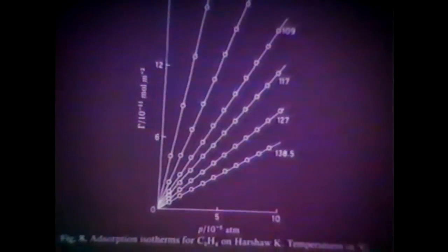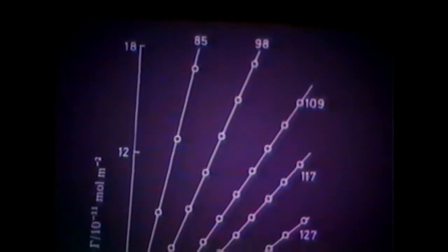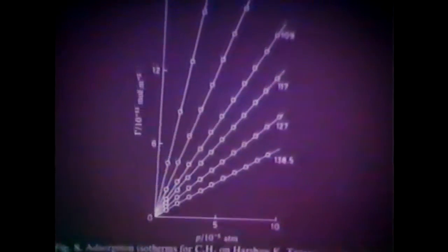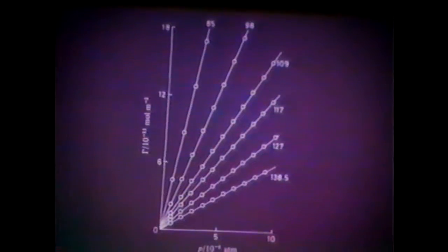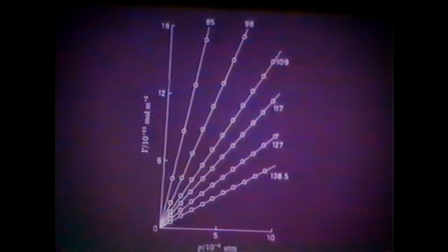That's with gas adsorption chromatography. I brought in ethylene here. It should have been water, but it shows quite nicely in the Henry's law region. The trick, or the method, with gas adsorption chromatography is to use the adsorbent as the stationary phase and elute the adsorptive. And from the elution peaks, it's possible to get the isosteric heat of adsorption.